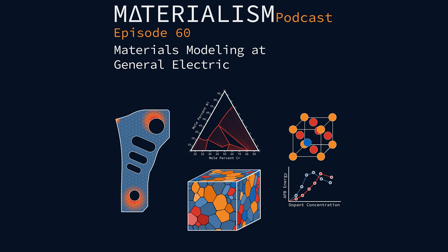So the little grains that are solidifying are now going to have a different composition than the regions around them. And you can actually see these in microstructures. If you look at them, you can see gradients in the composition that are strictly due to kinetics, essentially, what's happening here. So they assumed that that was what was happening here. They tested it. They actually did electron probe data, where you can look on a two-dimensional map at what the composition is doing. And sure enough, they saw evidence of elemental segregation.